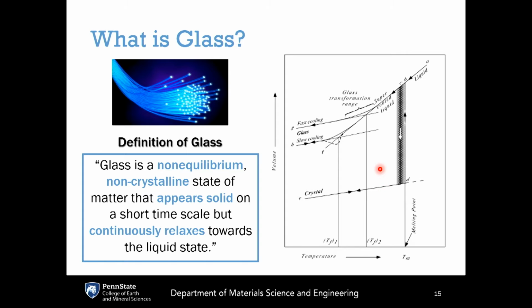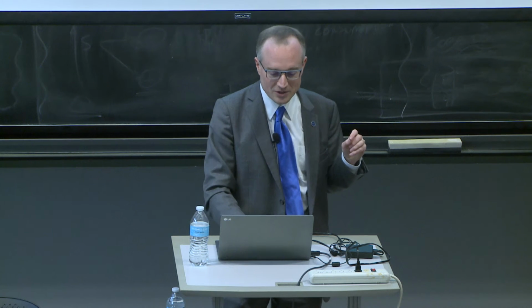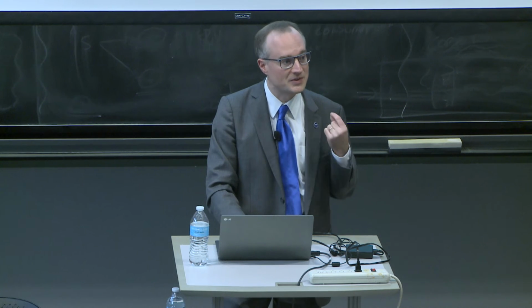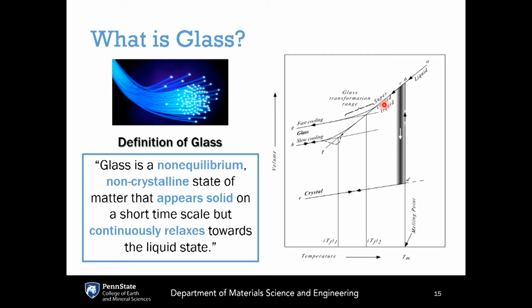namely the crystal. Now, if you take this supercooled liquid and continue to cool it, as you're cooling the system, you're extracting more and more thermal energy, and the atoms are no longer vibrating so fast, they're slowing down and getting really sluggish as they gradually get frozen in. Eventually, the time scale of this atomic motion becomes slow compared to your observation time scale. And when that happens, this metastable supercooled liquid, that structure is gradually freezing in.